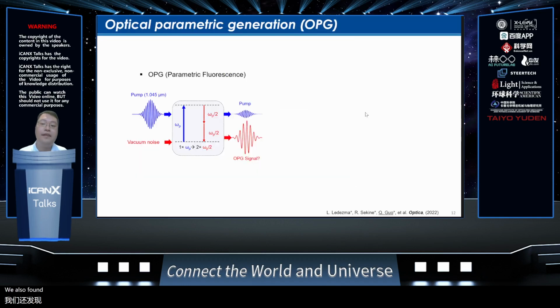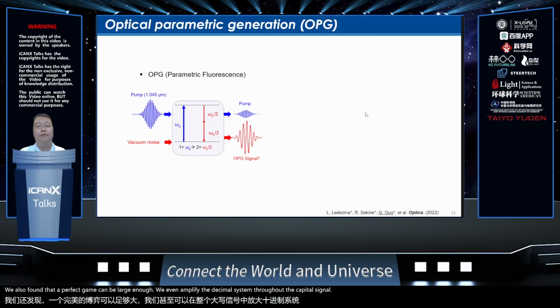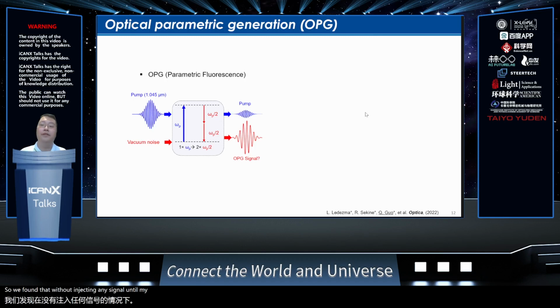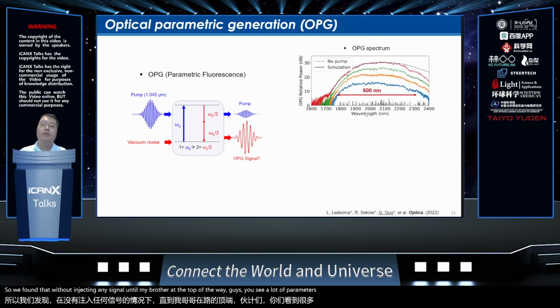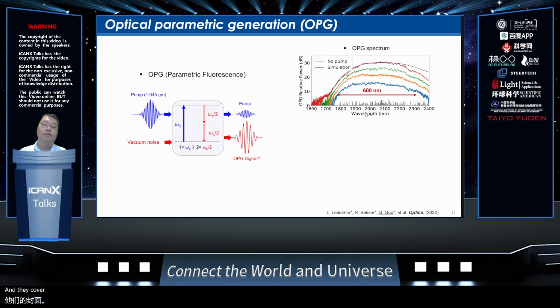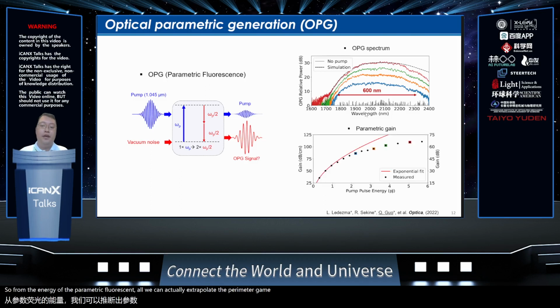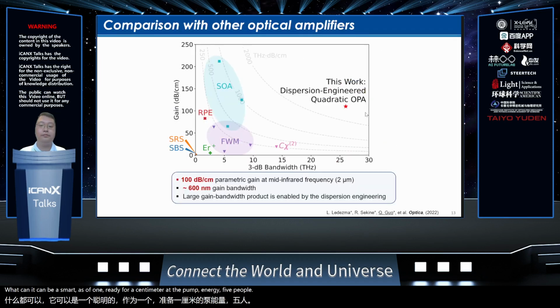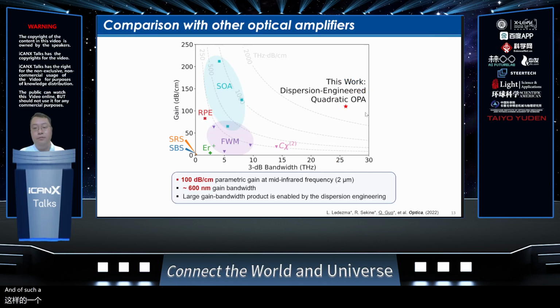We also found that the parametric gain can be large enough to even amplify the vacuum noise into a detectable signal. So without injecting any signal at 2 micron, at the output of the waveguide, we see a lot of parametric fluorescence at 2 micron. And they cover a pretty wide spectrum range of 600 nanometers. From the energy of the parametric fluorescence, we can actually extrapolate the parametric gain. We found it can be as large as 100 dB per centimeter at a pump energy of 5 picojoule. It turns out that our dispersion engineered OPA has the largest gain bandwidth product compared to all existing optical amplifiers. And such performance is the direct result of the dispersion engineering and the spatial temporal confinement we just